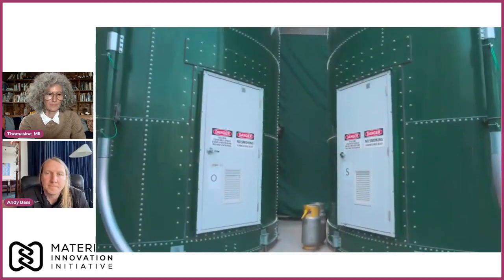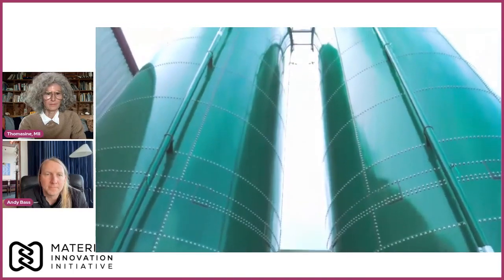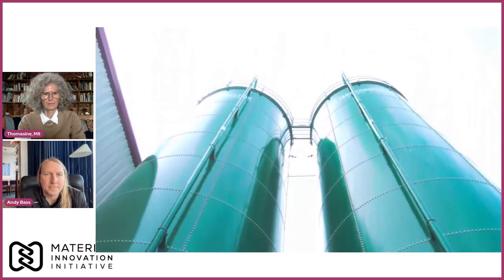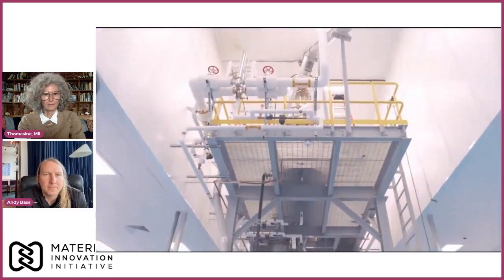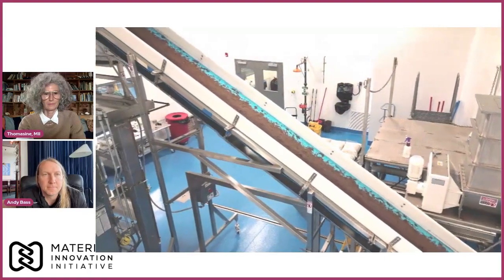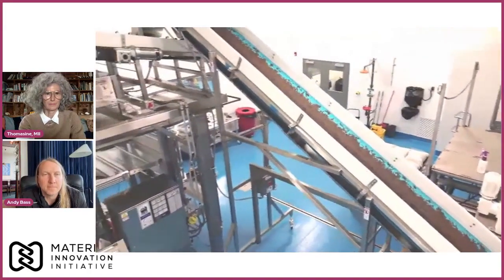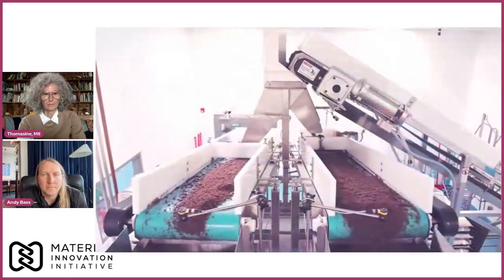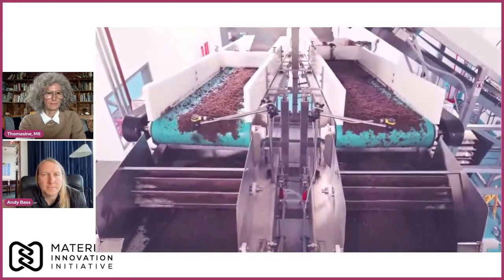In nature and in our farms, mycelium grows through wood chips, hemp stalks, and other organic materials. Our process starts with these raw ingredients stored in giant silos near Ecovative's headquarters in Green Island, New York. The raw materials are heat sterilized and mixed together with our specialized mushroom strains to grow 100% pure mycelium for our Forager Hides and Foams brand. Once inoculated, the material is carried by conveyors to be weighed, separated, bagged, and sealed.